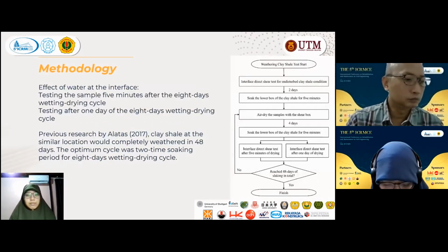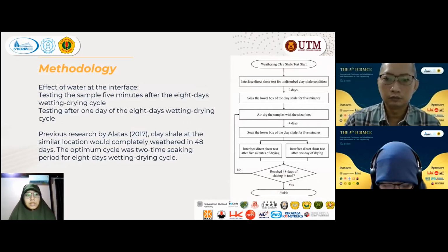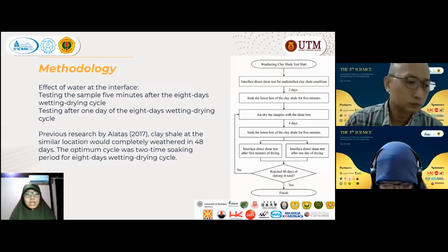So to determine the amount of samples, first of all, we conducted it with interface single-stage shearing. And second, we need to know the effect of water at the interface, which was differentiated into testing the sample 5 minutes after the 8 days wetting drying cycle and testing after 1 day of the 8 days wetting drying cycle. And as previous research by Alatas in 2017, clay shale at a similar location would completely weather in 48 days. So the optimum cycle was 2 times soaking period for 8 days wetting drying cycle.